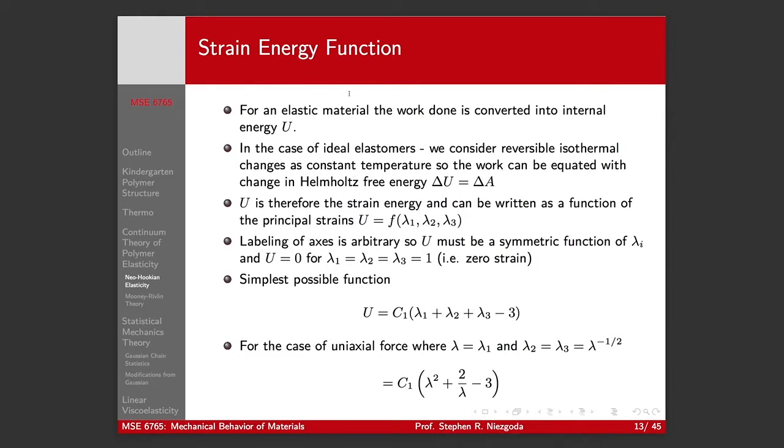So, going back to our strain energy function, remember I said a hyper-elastic material is one where you can derive the stress-strain relationship from a strain energy relationship. For a general elastic material, the work done is converted into internal energy. Now, in the last lecture I just said the change in internal energy is zero. Really, what we mean is a change in Helmholtz free energy. Before I was talking about this from a pure thermodynamic point of view, from a mechanics point of view, they also include strain energy into the internal energy. It's a change in notation. I was going from a materials point of view now to a mechanics point of view. I'm sorry if that's confusing. It's just different conventions from the different fields.